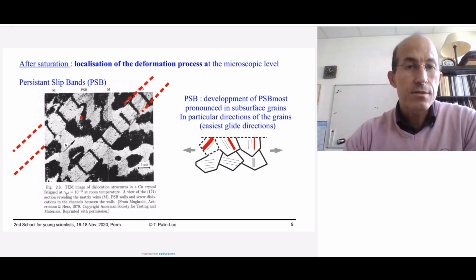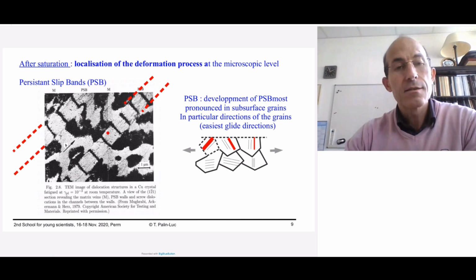After saturation, the localization of the plastic deformation process at the microscopic scale will lead to a collective behavior of dislocations that will create slip bands and then persistent slip bands. It means the collective behavior of dislocations will create in the crystals or in the polycrystals some veins which emerge at the surface of the material. You can see here a scheme of that.